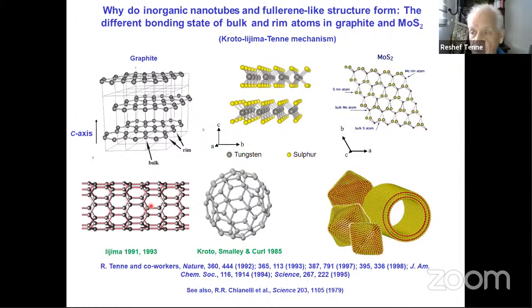Viewing these beautiful works, I decided to explore the possibility that molybdenum disulfide and tungsten disulfide will also form nanotubes. The reason being that they are also, like graphite, layered compounds. Here you have molybdenum or tungsten sandwiched between 2 layers of sulfur, so it's more difficult for them to bend and form nanotubes. But nevertheless, if you look at molybdenum disulfide from the C-axis, here you have one sheet of molybdenum disulfide. You see that the molybdenum at the edge is only 4-fold bonded, so 2 dangling bonds are missing. And the same is true for the sulfur. The sulfur is only 2-fold bonded instead of being 3-fold bonded as in the bulk.